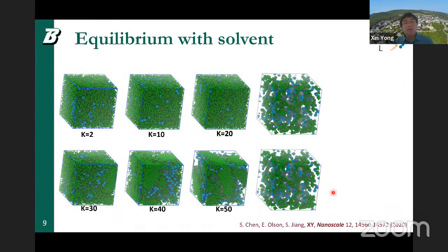And so we put together the polymers, and then we put together the particles. Here the green chains are the polymer, and the blue spheres are particles. More importantly, because in the experiment the films are formed by drying, by evaporation, we do consider the presence of solvent. So in all these cases, we first consider the equilibration of these multi-component systems with 50% solvent, which is not shown here. I will show it later. And then we vary the rigidity of the polymer and look at how the particles assemble themselves.